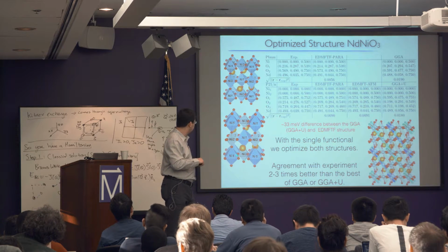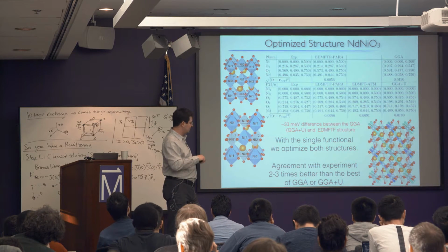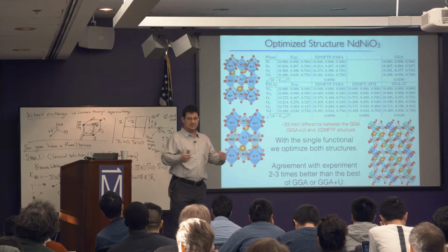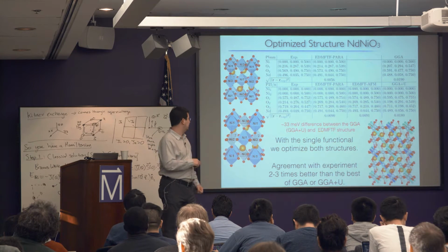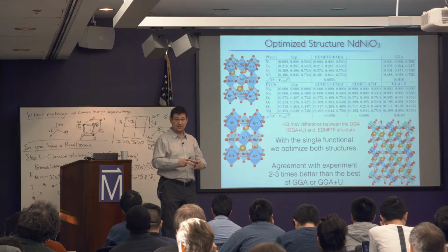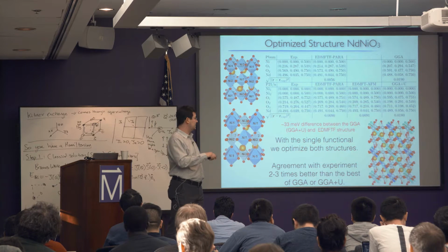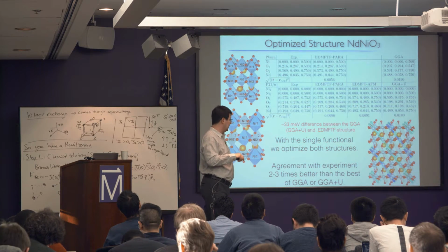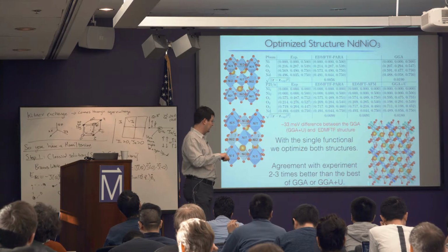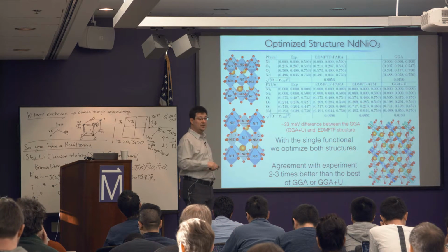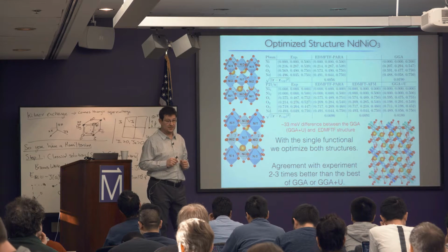At low temperature, it undergoes bond disproportionation, which means that one nickel octahedron is much bigger, and the second nickel octahedron gets squashed a lot. The question is, how well can one predict these structures? And then there's another structure, a magnetically ordered state, in which the unit cell quadruples. So we have 4 of those, 1, 2, 3, 4, and then certain arrangements of magnetic moments.